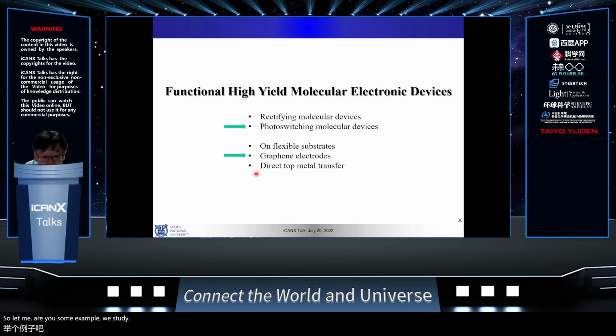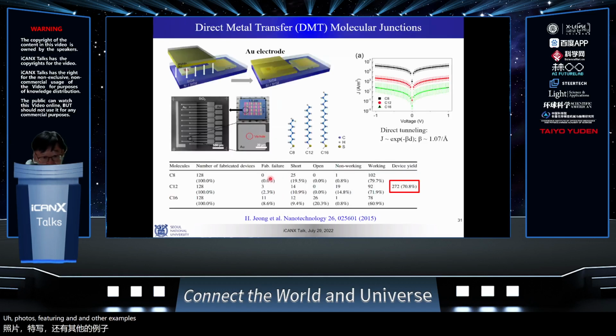We study using a high yield platform, either graphene or PEDOT:PSS conductive polymer or reduced graphene oxide spin coating, or many other ways. Photo switching and other examples. Okay. So one example: you can transfer not only graphene but also metals. So let's say we have a gold film on some layer of PMMA, then we transfer gold.